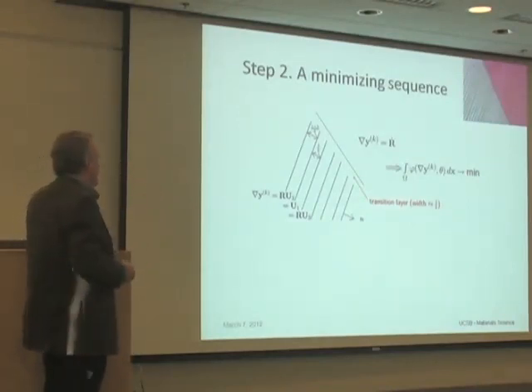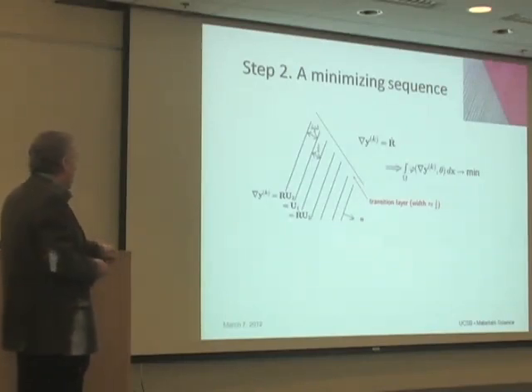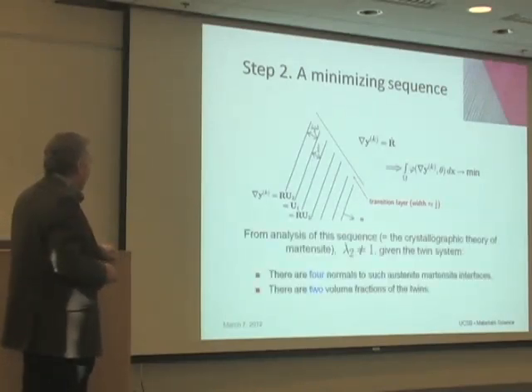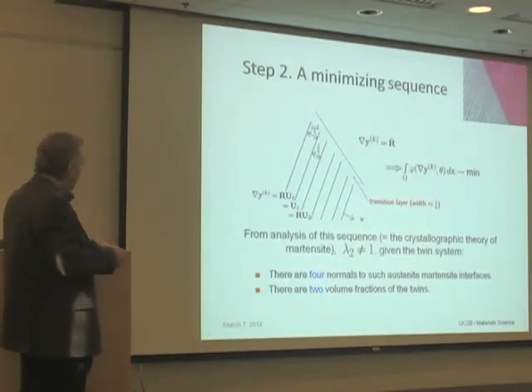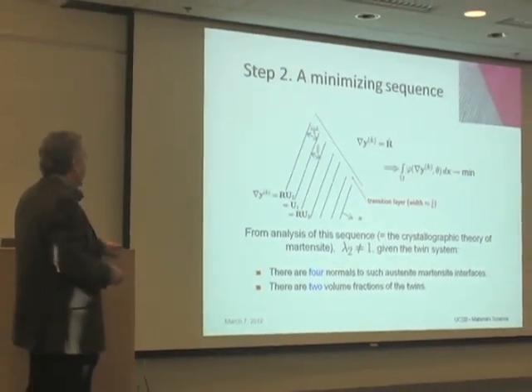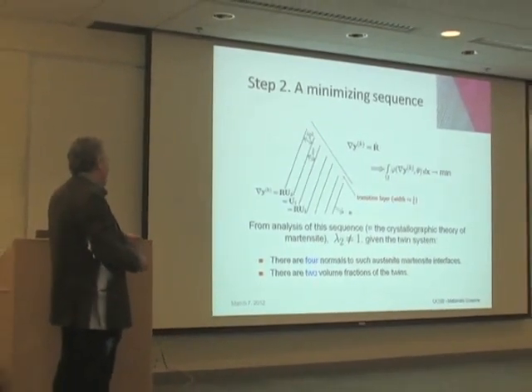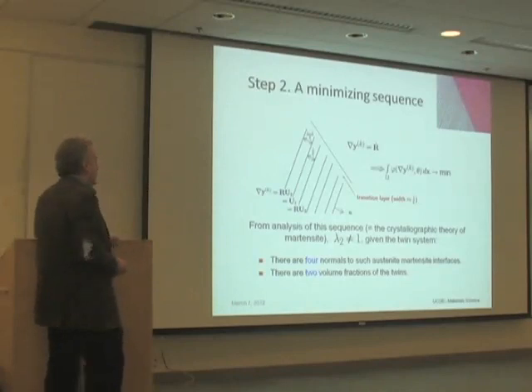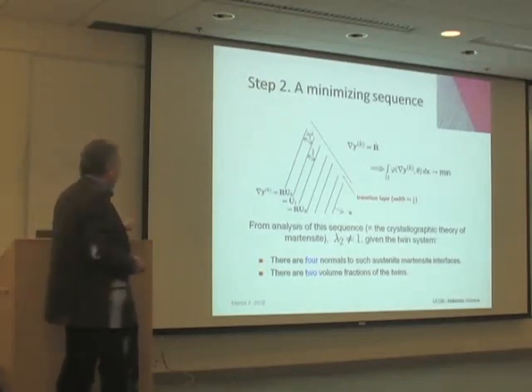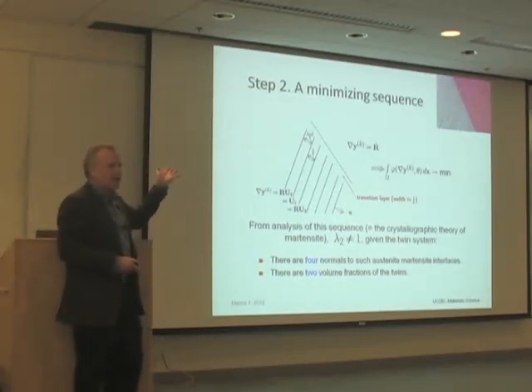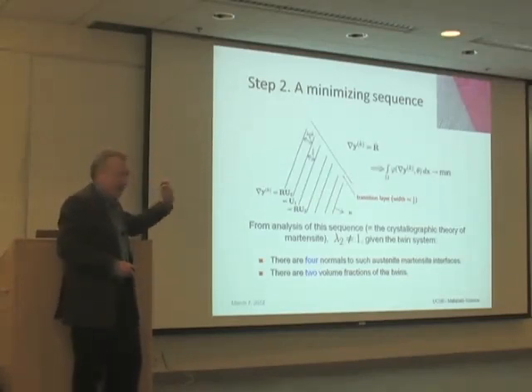Okay, now, and there's some results. This is all in the case lambda 2 is not 1. Turns out there are 4 normals to this interface. If you give the twin system, there are 4 normals. Correspondingly, there are 2 volume fractions of the twins. Okay, that's a bit technical. So that was considered a great advance somehow to explain that interface and so forth. But of course, this theory is a miserable failure about one thing.